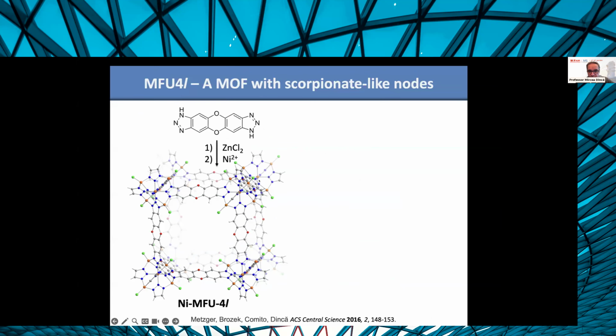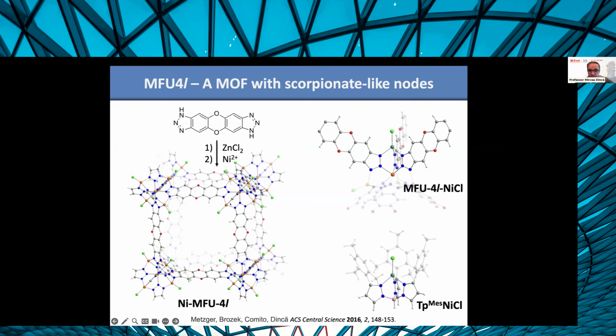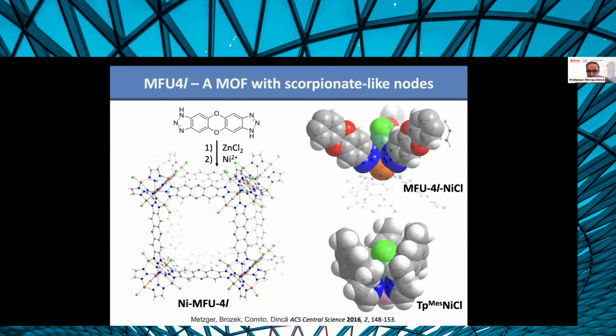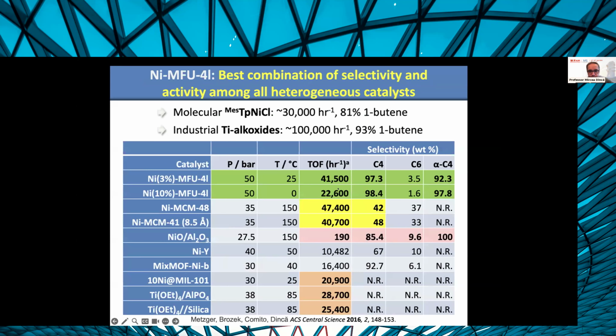It's called MFU-4l. It was originally made with zinc, but with our cation exchange strategy, we can implement it with nickel. And now the nickel MOF SBU has exactly the same structural features as the original molecular catalyst, but it works better because it's spatially more open, and that actually enables better selectivity than the molecular catalyst. So it turns out that this heterogeneous catalyst is better than the homogeneous catalyst and better than the existing industrial